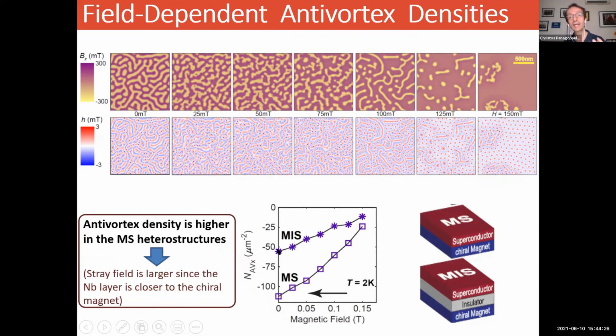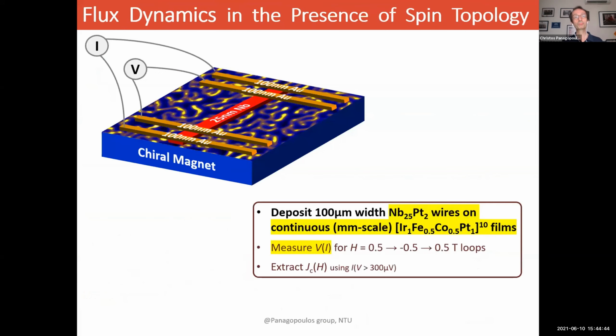Also, you find this anti-vortex density is higher in the MS heterostructures. And that is understandable because the stray field is larger, because the niobium layer in the MS heterostructure is much closer to the magnet. There is no insulator in between.